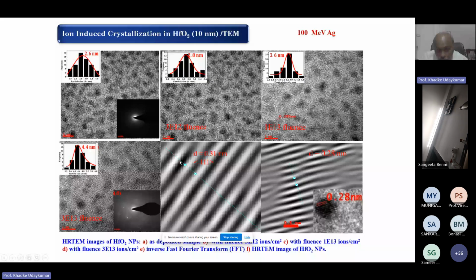No doubt the size of the particle is increasing, but between the particles, what is happening? There is erosion taking place, and this erosion is seen as a kind of ripple pattern of the order of 0.31 nanometer, seen at the orientation of the 111 direction. When you see the other direction, you can see that these ripple patterns are completely uniform in nature, and the distance in this erosion part is around 0.28 nanometer. Of this size, you will be able to create the patterning.